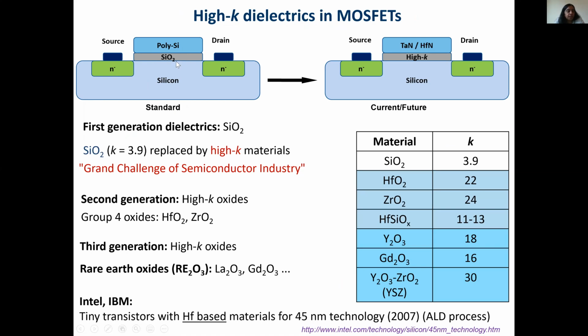And what was done in the past is that silicon dioxide was effectively used as a material to store charges, in simple words. You can see here a table with the material and an intrinsic property of the material called the dielectric constant. When you see the values, SiO2, silicon dioxide, has a value of 3.9. What happened is, as the device dimensions became smaller and smaller, because of the shrinkage of devices, at certain limits SiO2 will not be able to store the charges because it gets thinner and thinner. Every part of this device gets smaller. So there will be a limit reached and SiO2 has a breakdown.